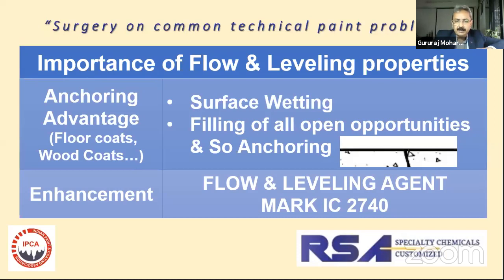I've made a very rough diagram here that you can see. This basically is a substrate, a concrete, which has a crack, and you have applied a coat on that. This coat, because of flow properties, has gone into the crack and filled it up. So when the paint sets or it's cured, this acts as an anchor. So it becomes a very good system to improve the life of your paint.